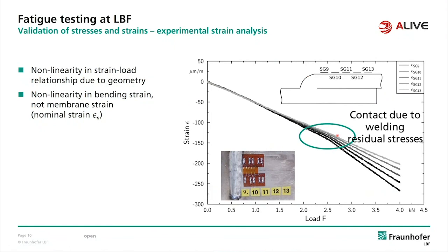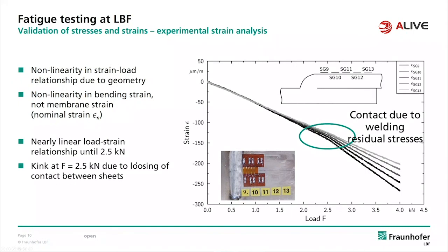So we have here in this area a kink in the slope between strain and load. So you can think, what is happening here? We see here the position of the strain gauges, strain gauge 9, 10, 11, 12, 13. And we see, oh yeah, there is something happening. And what is happening was identified. We see we have a linear relationship until approximately 2.5 kilonewton load, but then we get a different